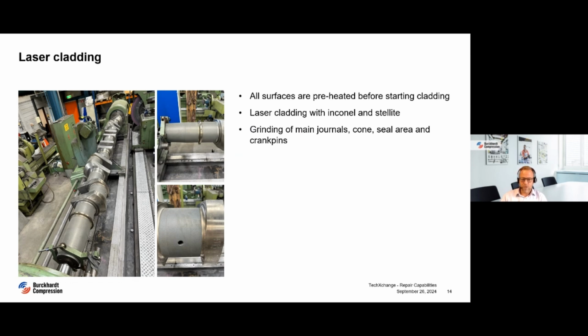At first, all surfaces are preheated before starting cladding. As opposed to many competitors, we preheat the crankshaft using induction. The preheating temperature can also be kept constant during the laser cladding. The big advantage of preheating to about 250 degrees and maintaining the temperature is that the risk of increased stress in the heat affected zone can be reduced by approx 20%.